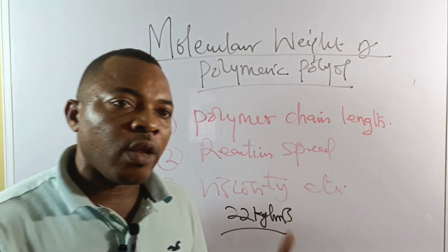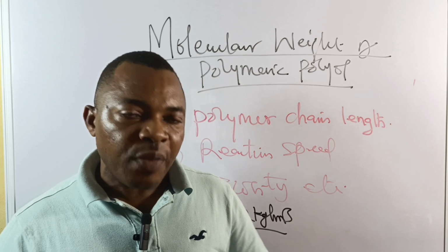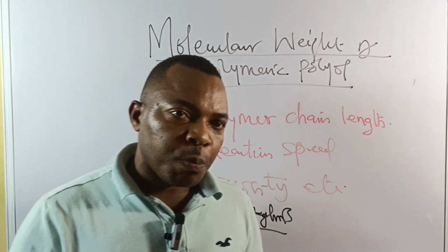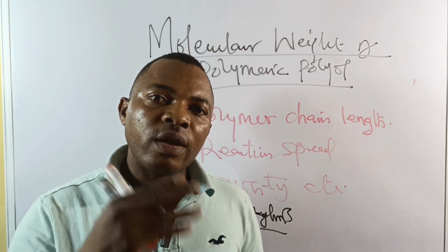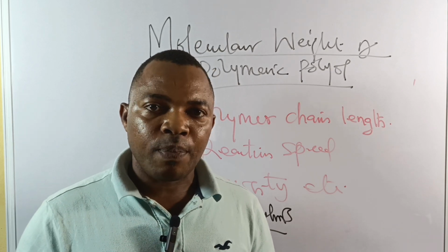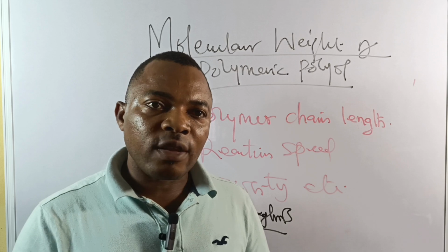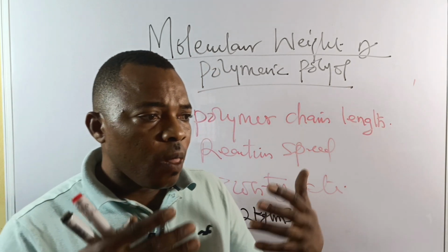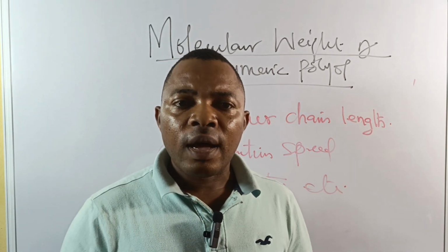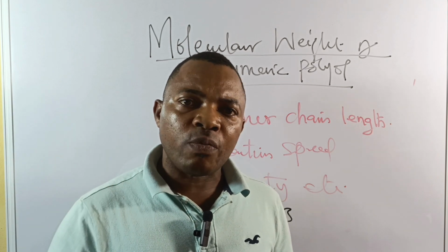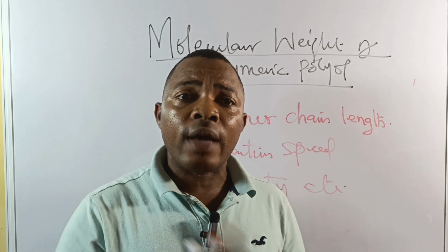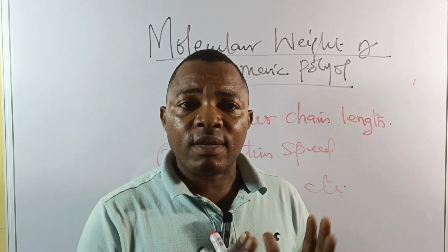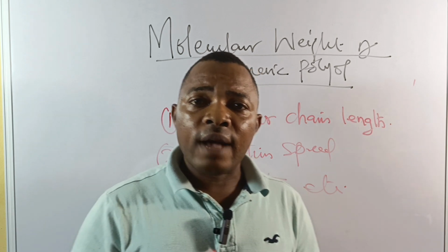Most of us also add a non-reactive filler like calcium carbonate into it. One of the things we should know is that when you increase your filler load in your foaming formulation, the reaction time will also take a longer time. So you have to ensure that your formulation is well balanced. I did say that increasing filler load in your foaming process is not the question. The question is that you have to select a good polyol and balance your filler blending excellently so that you will not have problems of split and crack, and at the end of the day, your mechanical property will meet up with the national standard of that country, because every country has its own national standard.